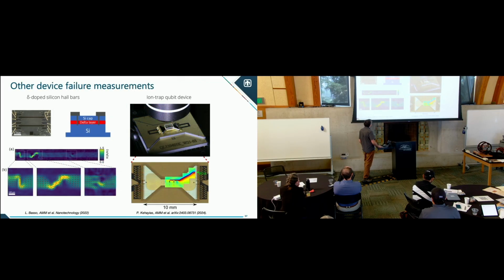experiments in this regard. One was from a group that does delta doping of phosphorus in silicon. We had these Hall bars, and we could actually see broken paths on this Hall bar from fabrication mistakes. So this was like a break in that, and so the current would go around this way and jog here. You're actually seeing the current in real space.